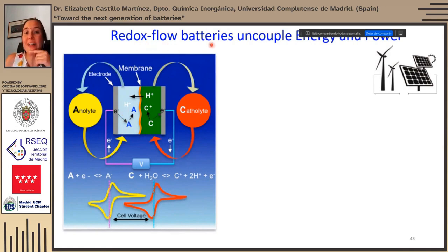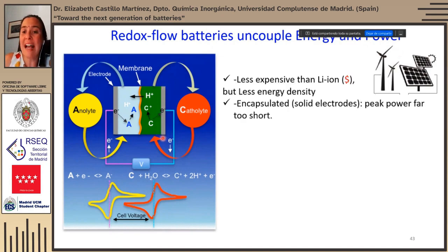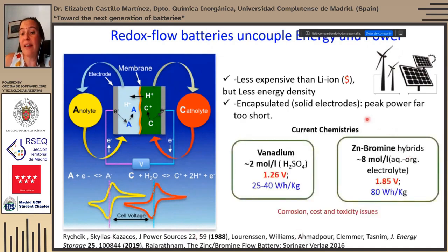So redox flow batteries can uncouple energy and power because the energy density is determined by the size of your tank, whereas the power is determined by the size of your electrode. And the current chemistries in redox flow batteries are vanadium, which is the most popular, in which you have the vanadium 2, vanadium 3 redox couple in the anolyte, and vanadium 4, vanadium 5 in the catholyte.